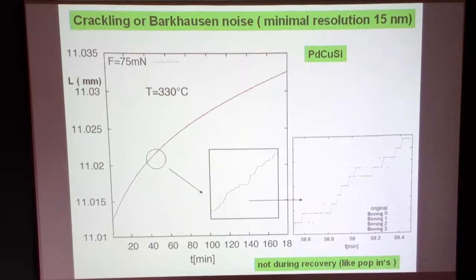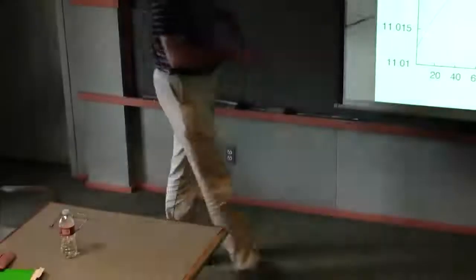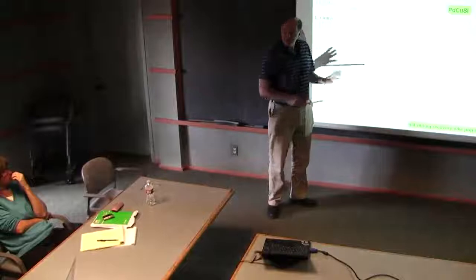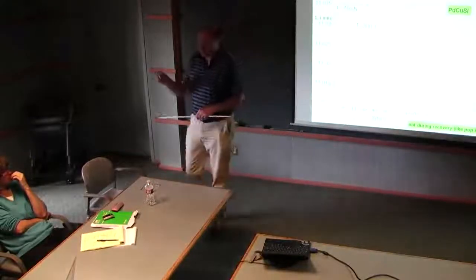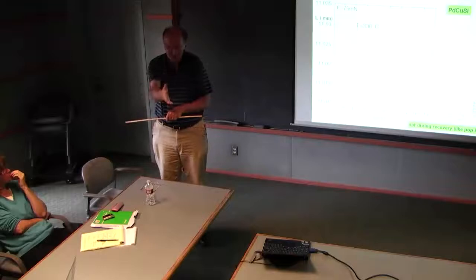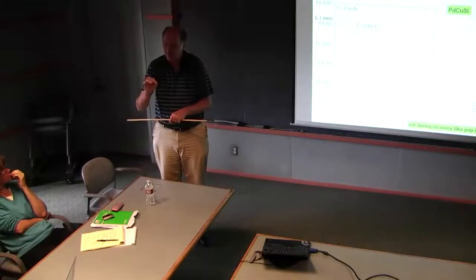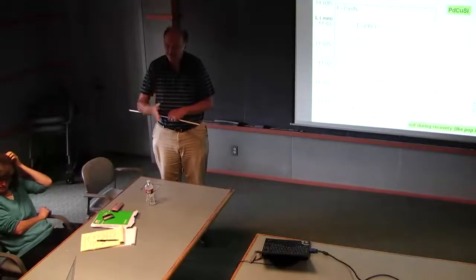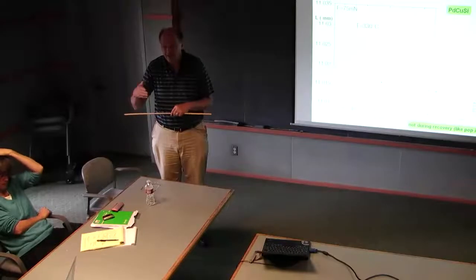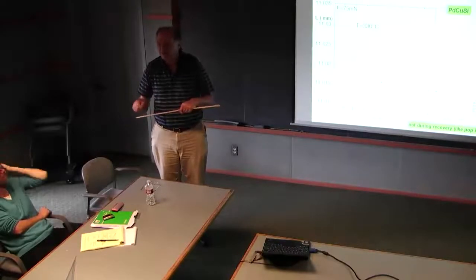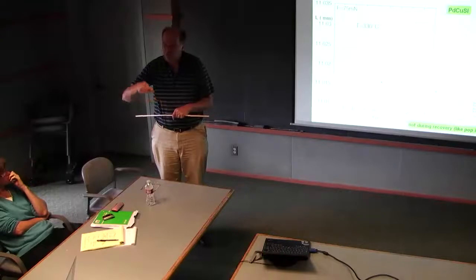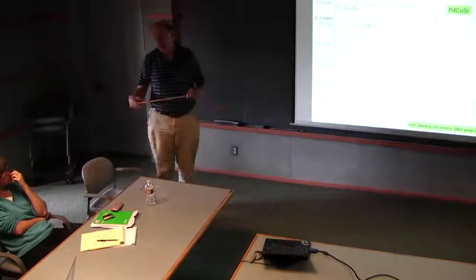Okay, that's a standard mean field. You talk about Barkhausen laws. How should I compare this with Barkhausen? Okay, from the statistics of the waiting times. Statistics of the waiting times is like you pull on the magnetic system and wait until the domain wall is moving. And there is a mechanic in the magnetic case. There's also creep. You have a creep relaxation if you excite the external field to a certain value and wait for the system to creep into that one.